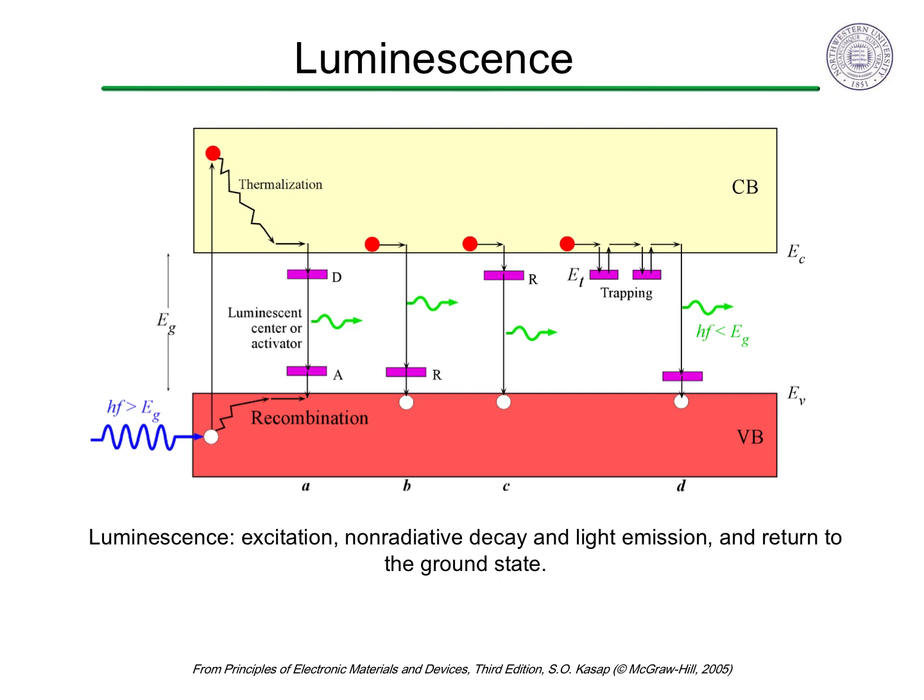Efficient, useful phosphors for luminescence often utilize electronic defect states. Structural defects like vacancies, interstitials, or substitutional point defects disrupt the electronic band structure locally and can lead to electronic states localized around the defect. The energy of these defects can be in the band gap, like electron donor or acceptor defect states. The luminescent electron transition that produces light can be between the defect states or between the band and defect states.